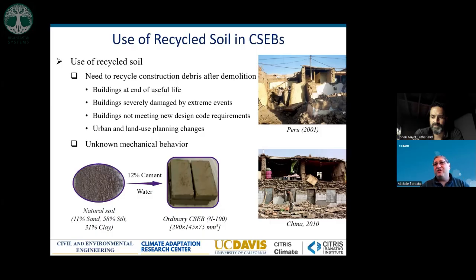And there are two different ways of doing it. One is putting it back into nature, which we are investigating, and then using it for making pristine blocks using the same soil without having to extract additional soil. Here, what we started with was natural soil, again, obtained locally with a pretty high amount of cement. Again, on-site, we would have used less, 12% cement.